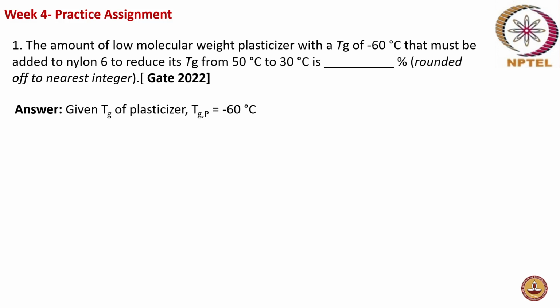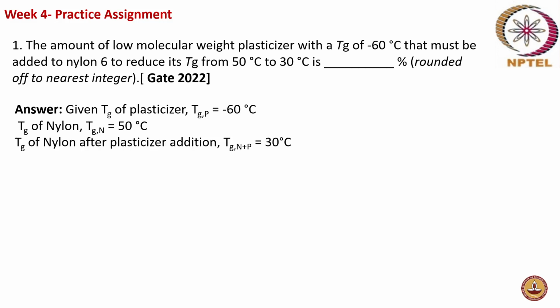So above minus 60 degrees itself, this plasticizer is very flexible. Correct. And then they have given the glass transition temperature of nylon, which is 50 degrees initially. Now this plasticizer is being added to nylon so that your glass transition is reducing from 50 to 30 degrees. Now we have to find out what is the fraction of plasticizer that is to be added so that this decrease in glass transition temperature of nylon takes place. So what is the weight fraction of plasticizer that is to be added?